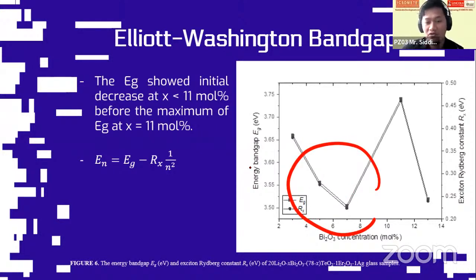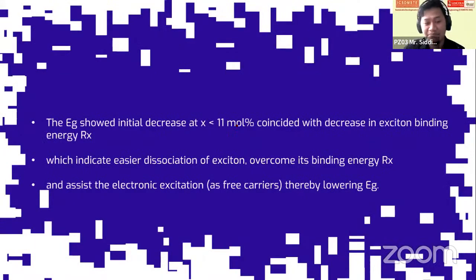So from this, we can conclude that whenever we have strong exciton-phonon coupling at some position, it can also help to reduce the energy band gap. It is actually good news to us because we can find one way to reduce the band gap of a material, especially in the glass field. You can see from here that the reduction in band gap coincides with a decrease in exciton binding energy. So it indicates easier dissociation or ionization of the exciton.